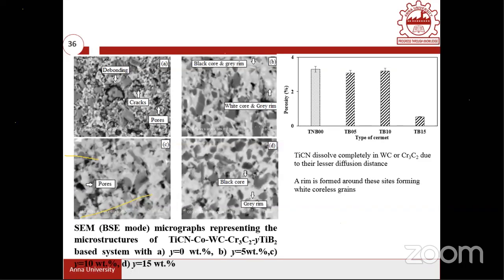Now here, the other case is TiB2. With variation in the TiB2, one can see the densification. See, TiB2 addition improves the densification, and also porosity is minimized, and no other carbon separation is taking place, because whatever carbon separates, probably it will give some other phases.